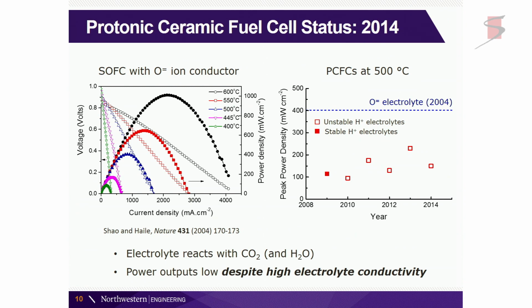So this is an example from my laboratory where we had a nice result, and numbers of laboratories have reproduced this result. The oxygen-ion conducting systems are doing quite well at this temperature, but the proton conducting systems were not doing well. So this was saying there's low power output despite this high electrolyte conductivity. In addition, we knew these materials were a little bit reactive with CO2 and steam, so that was also a detrimental feature of these electrolyte systems.